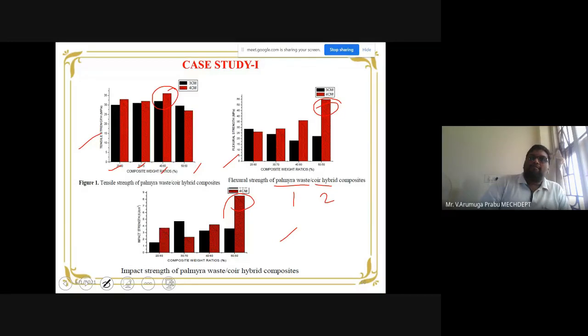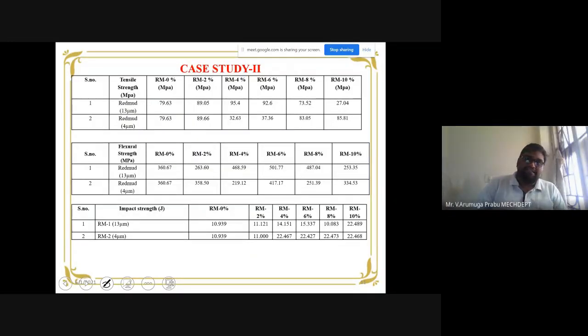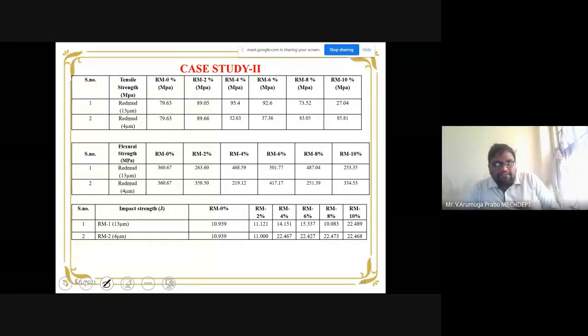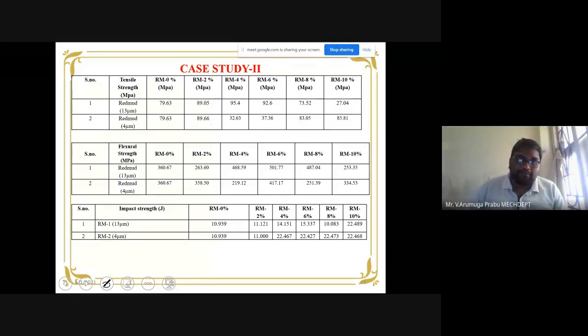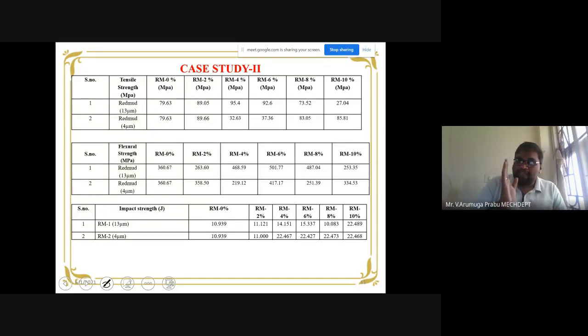So this again may be due to the incorporation of the Palmyra waste and coir in such a way that we are not able to obtain the final product in a properly uniform manner, in such a way that high strength is effective there. So this is one case study. And this is the next case study. What we did is, we add a filler along with the fiber and matrix, so that case 2 is another type of hybrid composite we prepare. See, my case 1 is purely the preparation of hybrid composites based on 2 natural fibers.